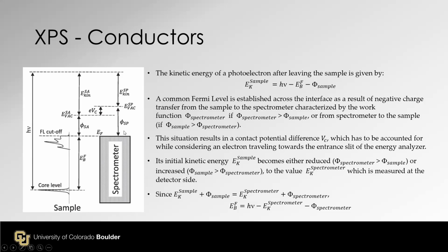From here, we know that kinetic energy of the sample plus work function of the sample, the sum of those two items should be same as kinetic energy that spectrometer can see plus spectrometer's work function. The sum should be the same.